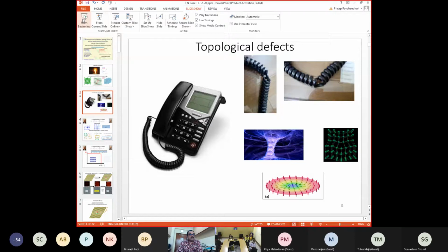These are some local defect here, but you cannot get rid of these kinks by doing something locally here. Because on one side of the kink, the wire is wound in one direction, in the other side it's wound in the opposite direction. So for example, if you have to get rid of these defects, then you have to unwind this entire wire in between and then wind it in the right direction. So these kind of defects, which are protected by symmetry, are what are called topological defects.